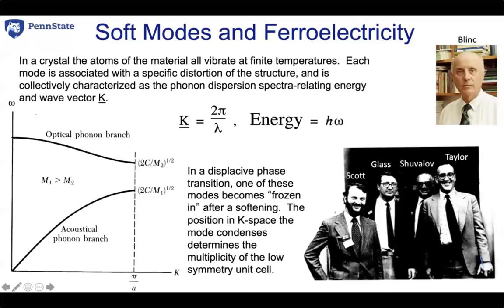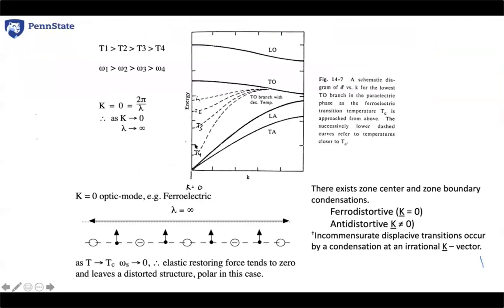This really took the understanding that we could take known phonon modes in ferroic materials, and we could begin to understand that some of the transverse optic modes slow down as a function of change in temperature. And we can think then of a locked off-center phonon mode as being the origin of the spontaneous polarization when that ferrodistortive mode occurs. The ferrodistortive mode will occur at k equals zero. The anti-distortive mode at a non-zero position in the Brillouin zone.